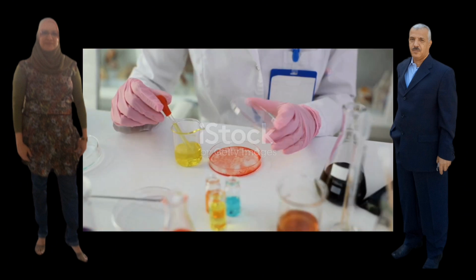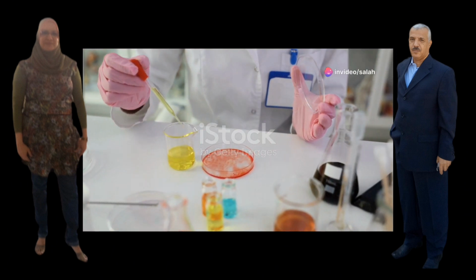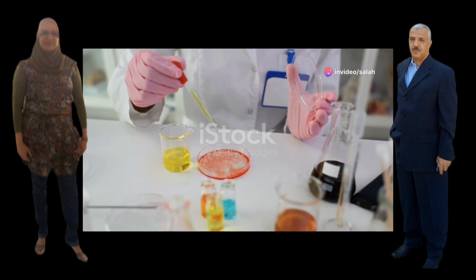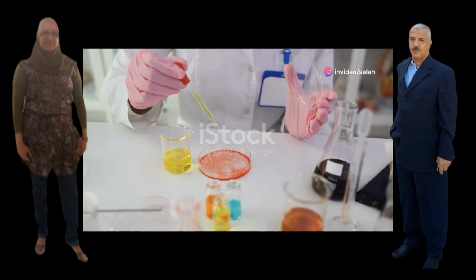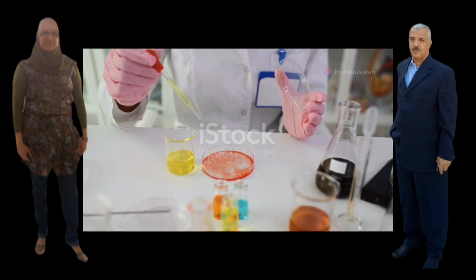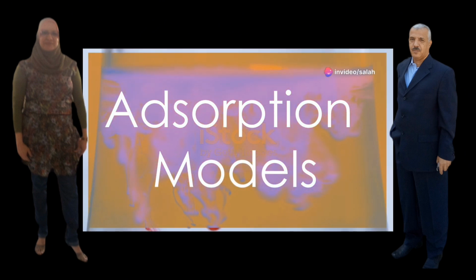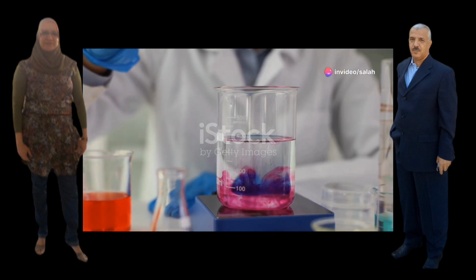In our sorption experiments, PVB-PEGDA copolymers demonstrated high sorption capacities for the diamine fast scarlet GG dye, especially those with higher PEGDA molecular weight. For diamine fast scarlet GG dye, the Freundlich model provided a better fit, suggesting a heterogeneous surface and multi-layer adsorption. Conversely, the adsorption of direct pink 3B was best described by the Langmuir model, indicating monolayer adsorption on a homogeneous surface.